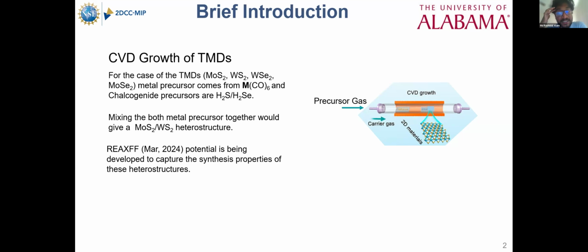When you add multiple precursors at the same time, you will see a heterostructure being grown. This heterostructure is an interesting material because these structures have multiple lattice parameters inside, which creates different strain in the material, and that creates interesting properties, like the band gap differing within the same material, and you will also see different phase transformations inside the material. The second interesting thing is that the growth parameters for both precursors and both species are different, so it is interesting research to tune these parameters and get proper growth.